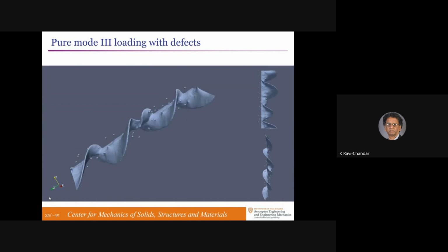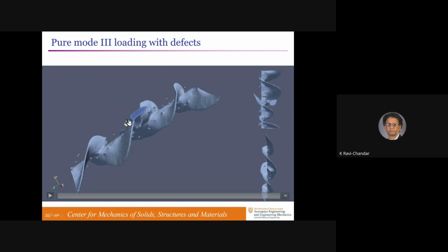And the daughter cracks, or the echelon cracks, appear automatically from just that small volume fraction of defected elements. Now, the overall size of our box was not large enough to let this go further. It's already reaching the upper limits of the box of our simulation at this stage, and this had 1 million elements or something like that. So that L0 not being very small prevented us from simulating very large domains,